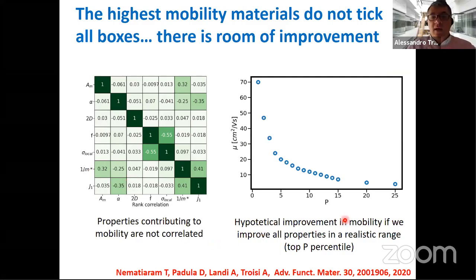However, and for this reason, we can create a hypothetical experiment where we take all the parameters and we make them better in parallel within a reasonable range. So this is the mobility that we will get if all parameters were set to be in the top 15 percentile, 10 percentile, or 5 percentile. And this is the type of improvement that we expect as physically possible and statistically possible from the data set of materials. So we can actually not only make predictions of selected materials, we can also set the achievable target for the entire class of materials because we have looked at all of them, so we know what is achievable in terms of parameters for each one of them.